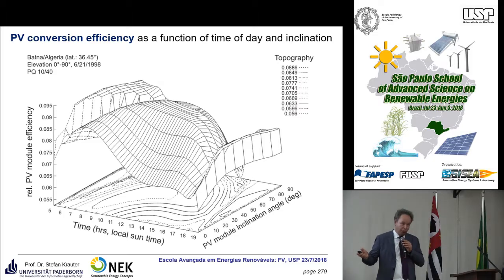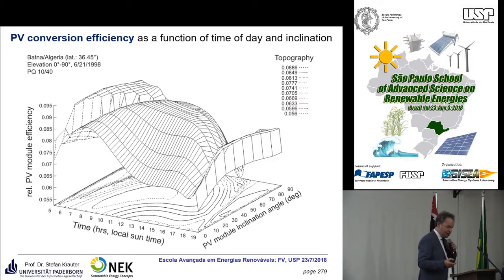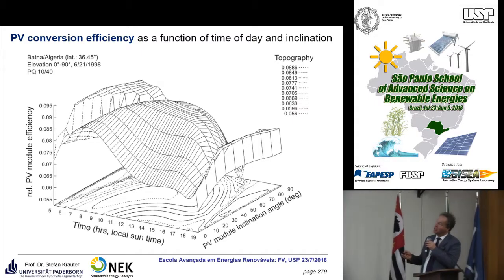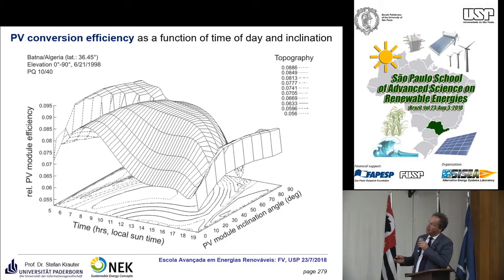But this you can optimize not only in terms of irradiance, you can also optimize it in terms of thermal optimization of the PV system. Interestingly, here before sunset, there is some diffuse irradiance. This works quite well because the module is cold. And here you have a very small optical efficiency because you have high reflection. Because in the morning, the sun is quite low, the inclination angle is low, and there are a lot of reflections, and therefore there is an efficiency drop here in the morning. As soon as the sun goes up, the efficiency also goes up.